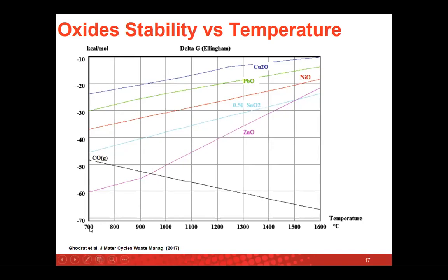For example, at 700 degrees centigrade, we can see zinc oxide is the most stable compared to carbon monoxide. But when we increase the temperature to about 955 degrees centigrade, roughly, thermodynamically, we can say that carbon monoxide is the most stable oxide compared to zinc oxide, tin, lead, copper, nickel. All of these oxides are present in the copper scrap in the copper smelting route.